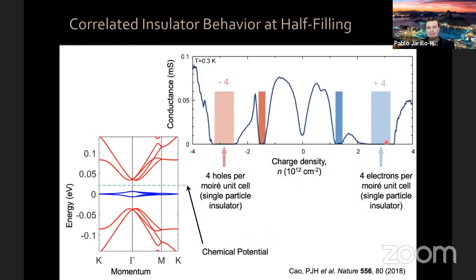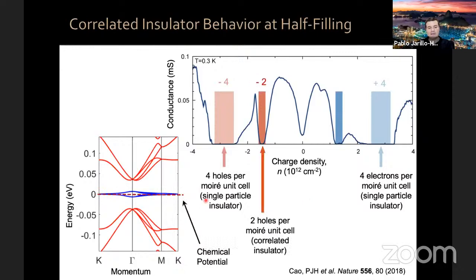Now, if we put the chemical potential here below charge neutrality, in the middle of the valence band, when we add exactly 2 holes per Moiré unit cell, the chemical potential is in the middle of a band. We should be conducting very well. This should be a metal. However, we also have 0 conductivity. This happens to be a correlated insulator state that appears when we put 2 holes per Moiré unit cell.